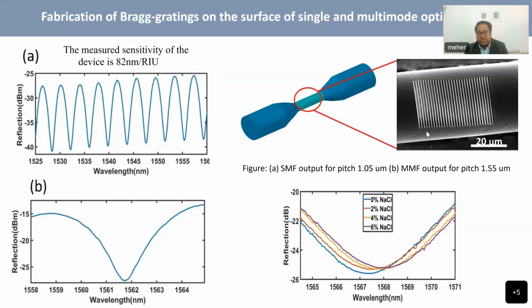You can see very nice patterns on the core of optical fiber. And this is around 20 microns. So you can see how miniaturized this device is. And we actually played in the micro and nano regime when we fabricated this.